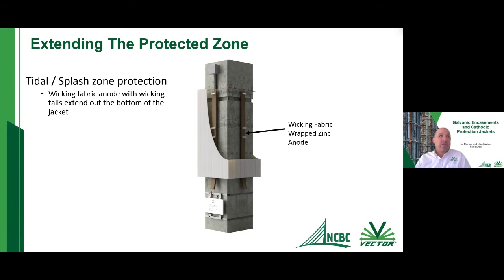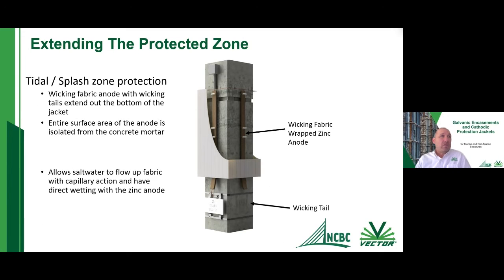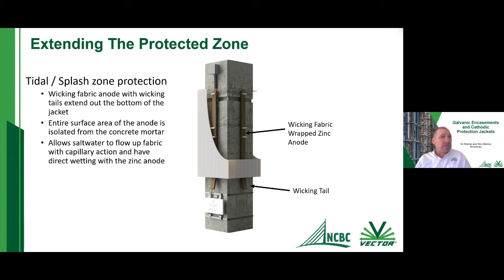And then this is just kind of a detail of how it's installed or the parts of the system. So basically you have a wicking fabric that's attached to a pile. It is hung on a pile, and you're going to determine in your design whether you're going to use 1 per face or 2 per face, and depending as well if it's a round pile. So you're going to do a design to figure out how many anodes, or Tidal Plus anodes, are going to be required. There's also going to be the stay-in-place form that's going to be used.